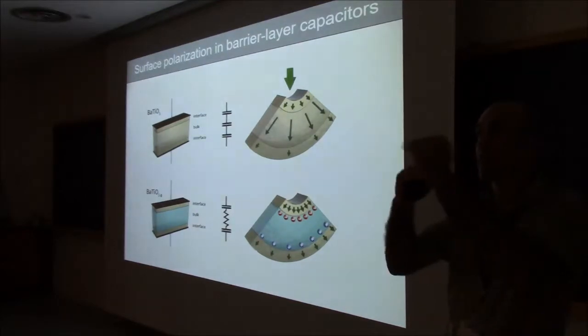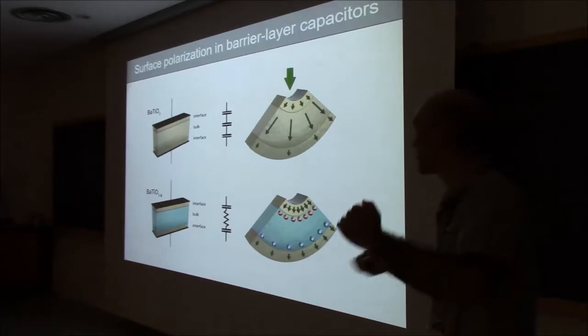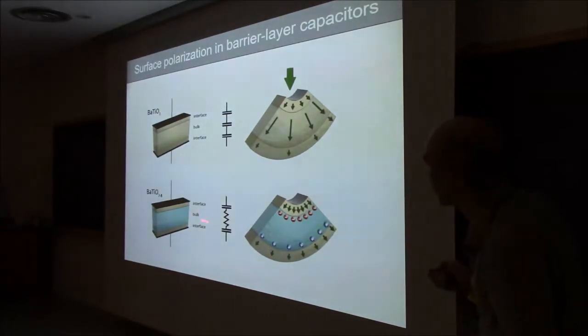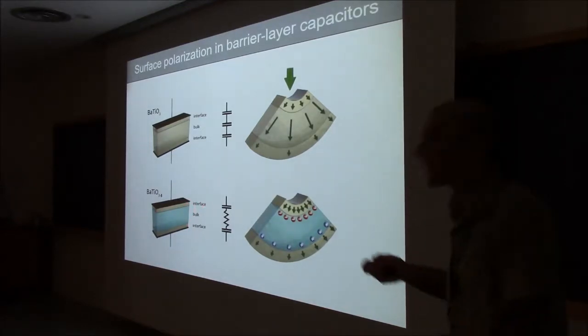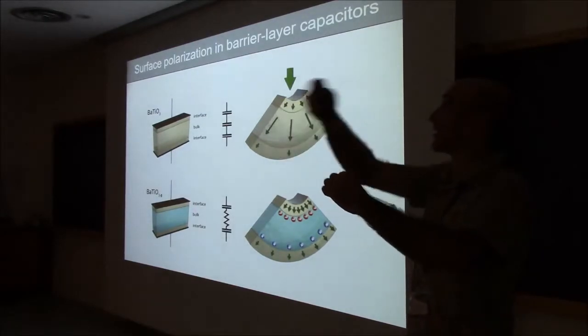The interface may still be insulating because basically you have a barrier layer, a Schottky contact between a metal and your semiconductor. Okay, so let's assume that the surface is still insulating. So your effective capacitor is now only the interface region. And because the interface region is very thin, the capacitance is very big. That explains the Maxwell-Wagner effect. That's what I explained 2 days ago.